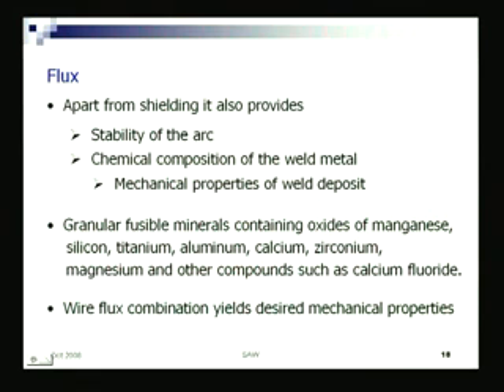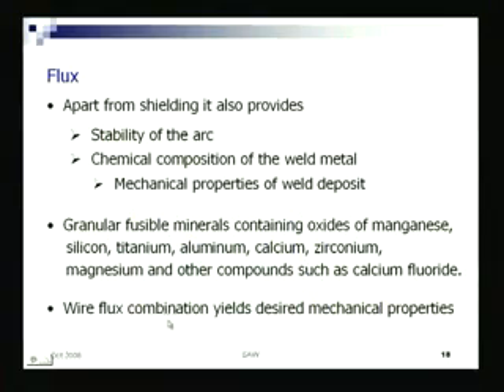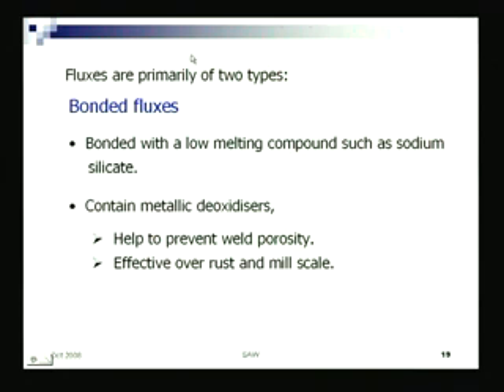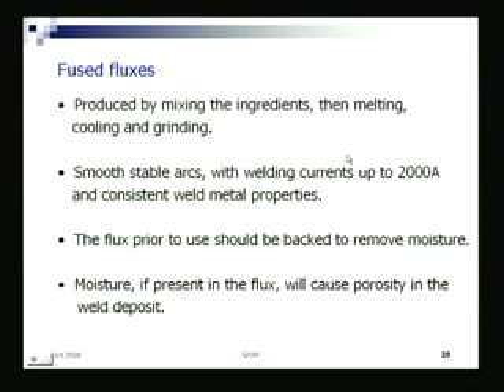And then you have the so-called wire flux composition. For welding a certain material, whatever mechanical properties are desired, you use a suitable wire flux combination, as we have already talked about. There are generally two types: there is a bonded flux, bonded with a low melting compound, and there is a fused flux.